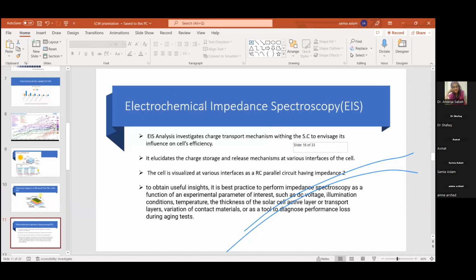It elucidates the charge storage and release mechanism at various interfaces of the cell, and the cell is visualized at various interfaces as an RC parallel circuit having an impedance Z. So to obtain useful insights, it is best practice to perform impedance spectroscopy as a function of an experimental parameter of interest, such as DC voltage, illumination conditions, temperature, the thickness of the solar cell active layer. This is the layer where the absorber material is pasted, or the transport layers, variation of contact materials, or as a tool to diagnose performance loss during aging tests.